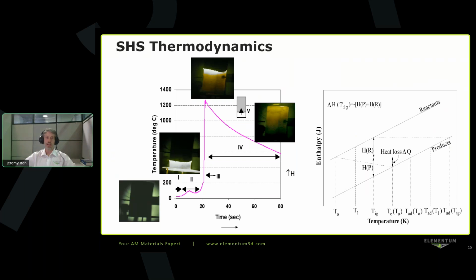So if you had a thermocouple on that pellet that I showed reacting just a minute ago, this is kind of what you'd see. Initially, you would be at the starting temperature, and then you'd have a very rapid spike when the reaction wave is passing or taking place in your temperatures until you achieve your combustion temperature, and then you'd have a slower cooling process. And again, this is the propagating type mode. In a laser powder bed fusion, all of this is taking place much more rapidly and only locally within the melt pool on about 100 micron scale.